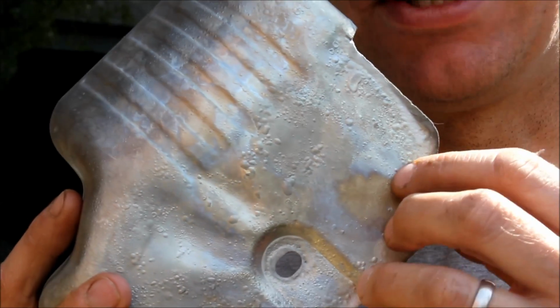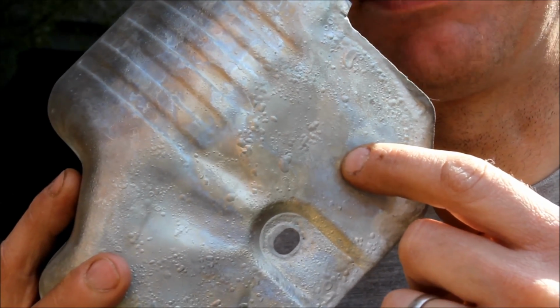There's hydrogen gas coming off it, and that gas is blistering the plate, it's lifting the plate straight away. Now usually adhesion and blistering problems like we just saw there are caused by poor cleanliness. So if you've got blistering, the first thing to check is whether the part's clean enough when it's going in the bath. However, with that heat shield, it's scrupulously chemically clean when it's going in the bath.